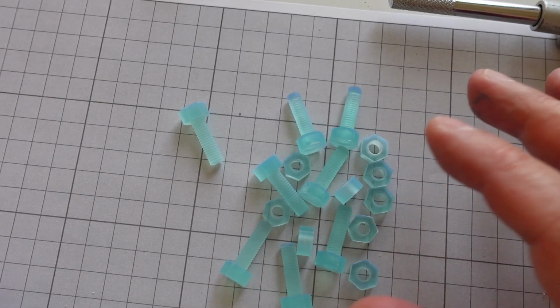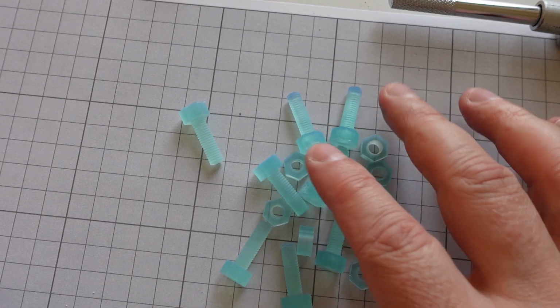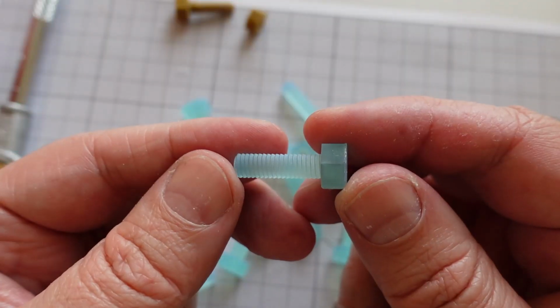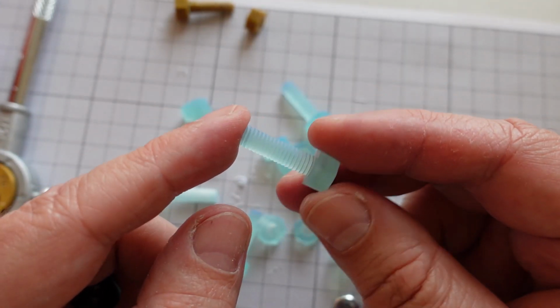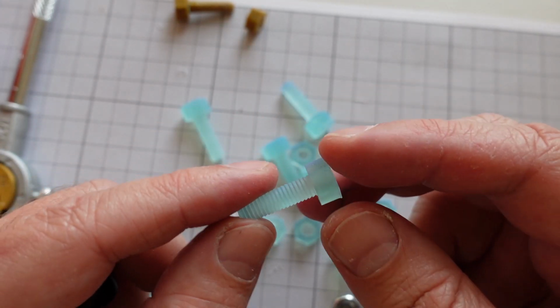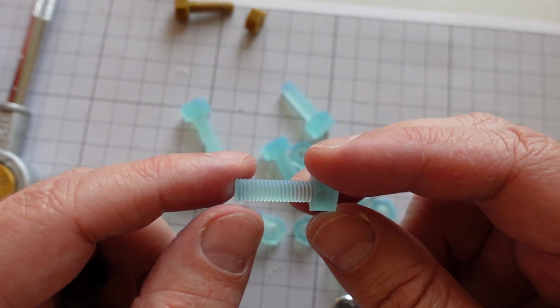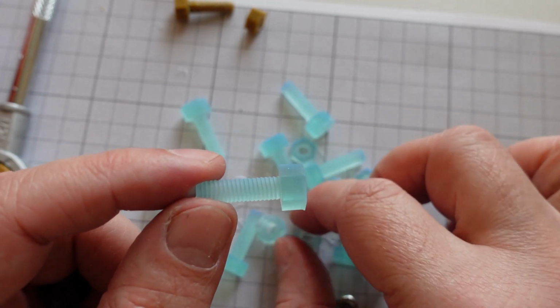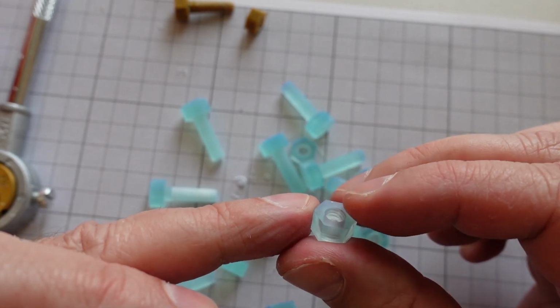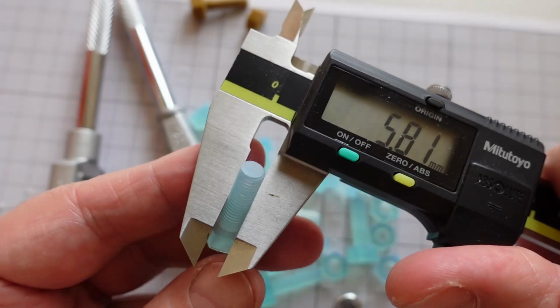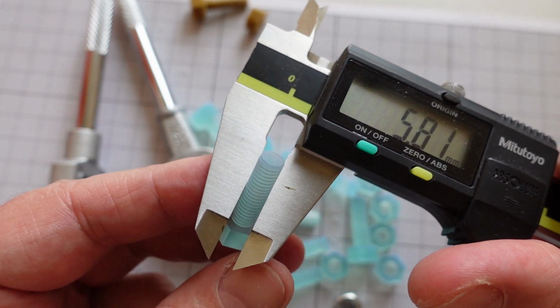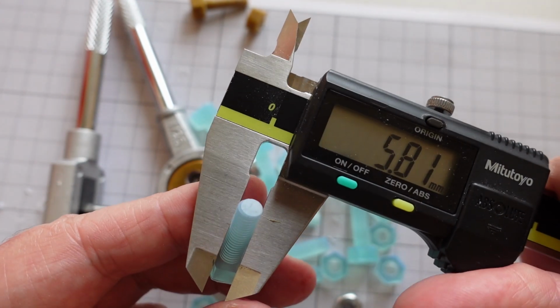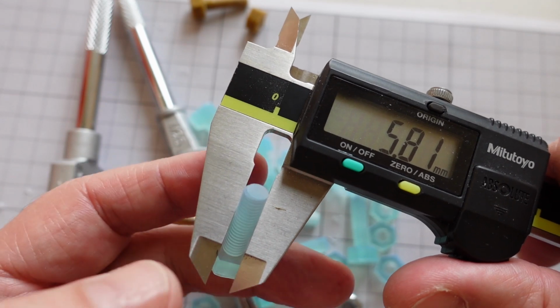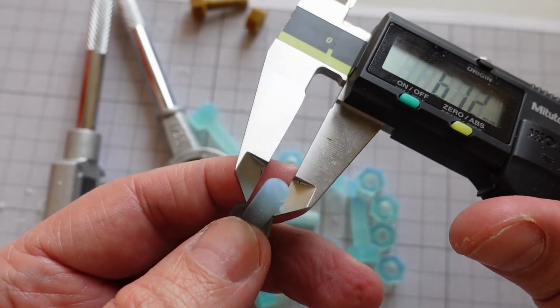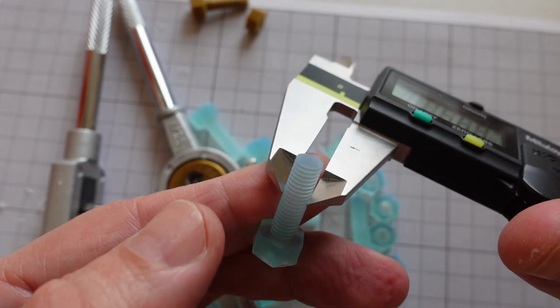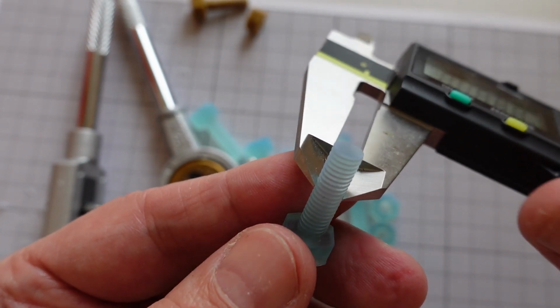And this is the Siraya Blu and Tenacious mixture, 50-50%. Unfortunately, I didn't add any clearance. I wasn't sure how this resin would print. So I have to clean the thread both in the bolt and in the nut, inner and outer threads. Well, actually, the outer diameter is good because it is 6 mm with negative tolerance. So it must be the minor diameter, which I cannot really measure with this caliper.